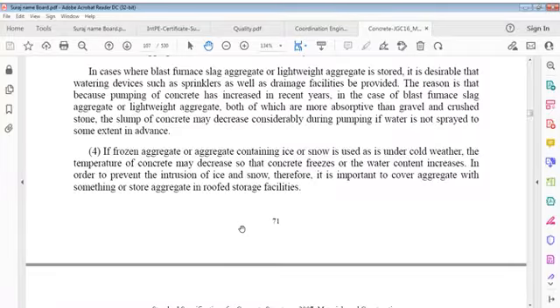The reason is that because pumping of concrete has increased in recent years, in case of blast furnace slag aggregate or lightweight aggregate, both are more absorptive than gravel and crushed stone. Slump of concrete may decrease considerably during pumping if water is not sprayed to some extent in advance.